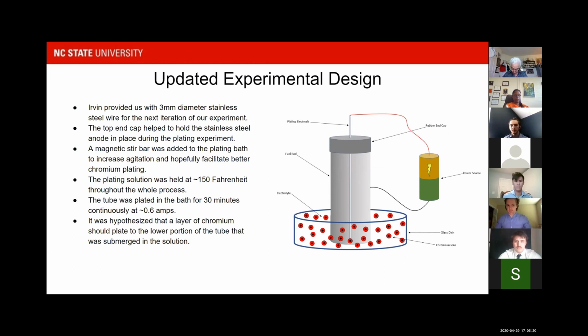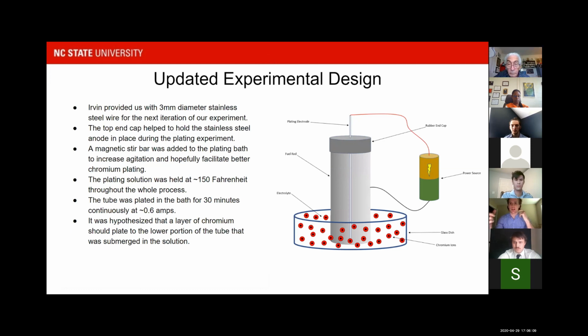After taking this into consideration, we decided to make a modification to our initial experimental setup. What you'll notice is different is that, rather than having two end caps, one on the top and one on the bottom, we removed one of the end caps, left the bottom portion of the tube open, and placed it in a dish of chromic acid plating solution. The reason for doing this was to ensure, A, we wouldn't have evaporation of the solution as we had in our initial setup. B, we could agitate the solution with a stir bar, so solution could freely move in and out. We wouldn't get any sort of local depletion.